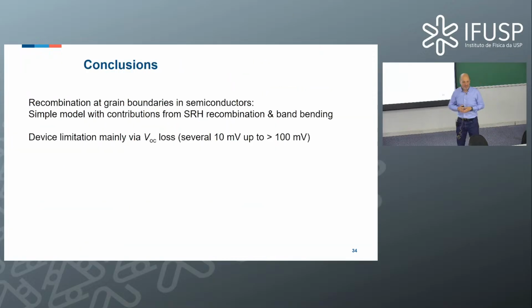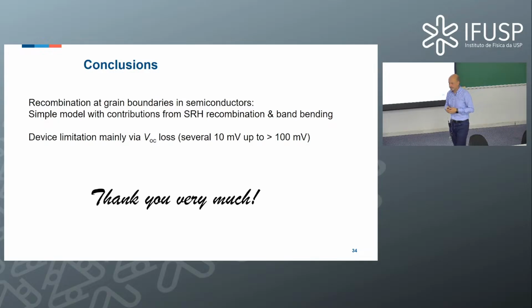Okay, so conclusions. Yeah, we saw recombination at grain boundaries. I showed you examples from semiconductors used for photovoltaic absorbers, but we can actually apply this model to each and every semiconductor. It's a simple model. It has 2 parameters, in very short form, and there are always 2 contributions: the Shockley-Read recombination in the prefactor, and band bending, which is contained in the exponential function. And the device limitation is mainly via the voltage of the device. And voltage losses range from several tens of millivolts up to more than 100 millivolts, depending on the material system.